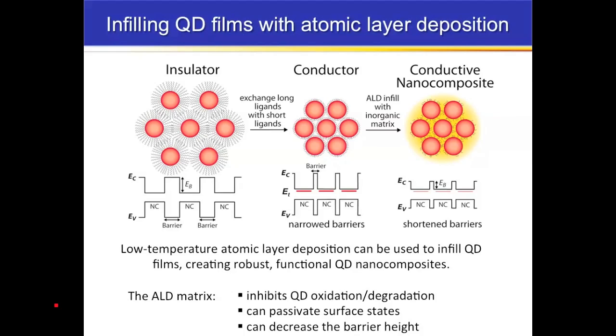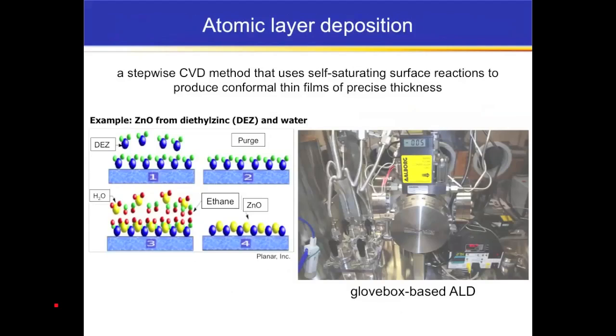The second thing that it can do is passivate surface states that are on the outside of all these dots. If we choose the right material, we'll passivate surface states that'll raise the mobility. And again, if we choose the right ALD material, we can decrease the barrier height. So alumina is not a good choice to do this, but other smaller gap materials are good choices. And so we built an atomic layer deposition system in our glove box to be able to do this without exposing our materials to air.